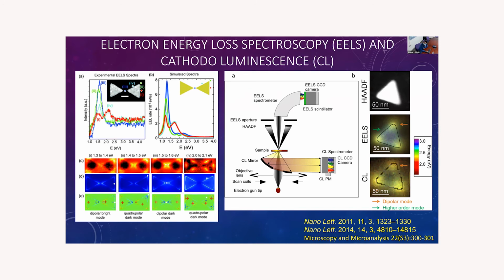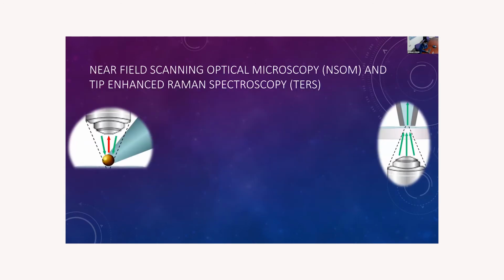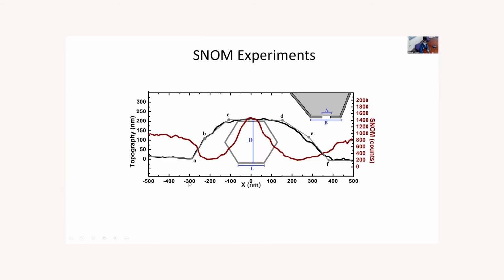There are some other approaches to measure the near field directly, using probe microscopies. I will show you two kinds of this microscopy with some examples: TERS spectroscopy and SNOM microscopy. In the case of SNOM, with Professor Goñi, a couple of years ago, we did some experiments using the SNOM that we have in the group. The system in that case was zinc oxide nanowires.